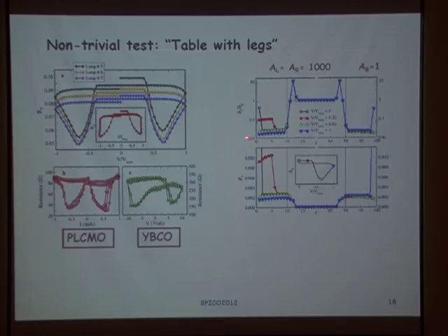So here I'm going to go a little bit deeper into the details of why we obtain these loops and why these loops are correlated with the density of vacancies, or with the local resistivity along the sample. For example, I'm going to show one of these loops and follow it as a function of the voltage. From these different marked points, I'm also showing the local density of vacancies along the sample and the local resistivity. Of course, the local resistivity is proportional to the local density of vacancies.